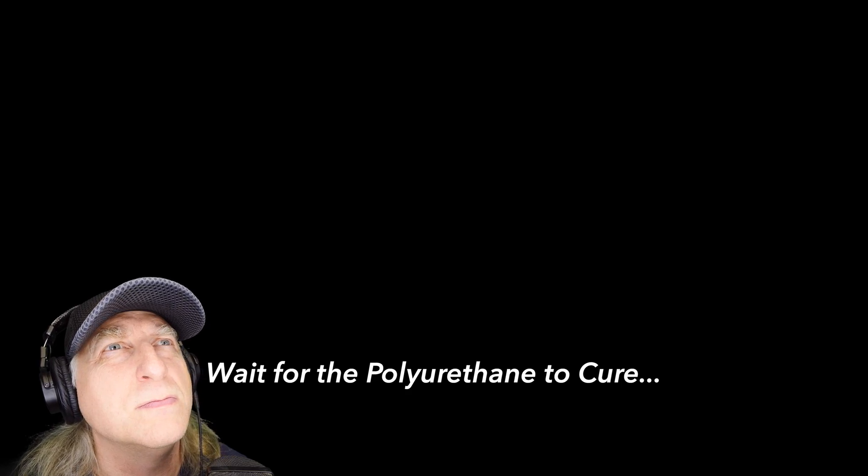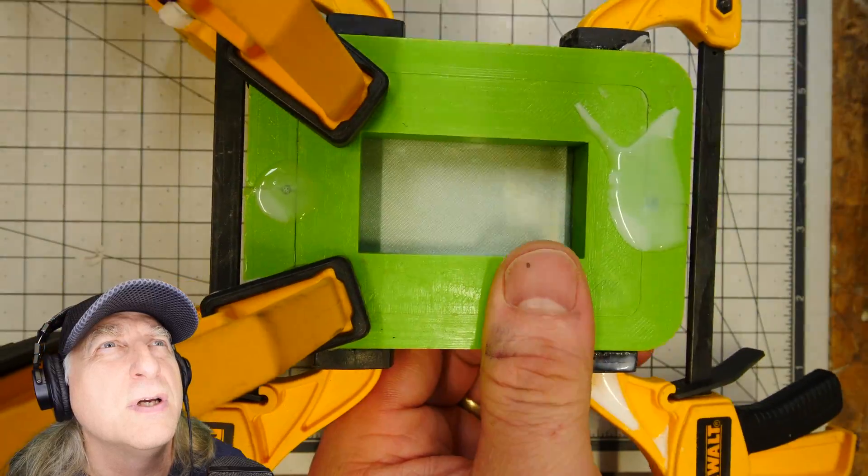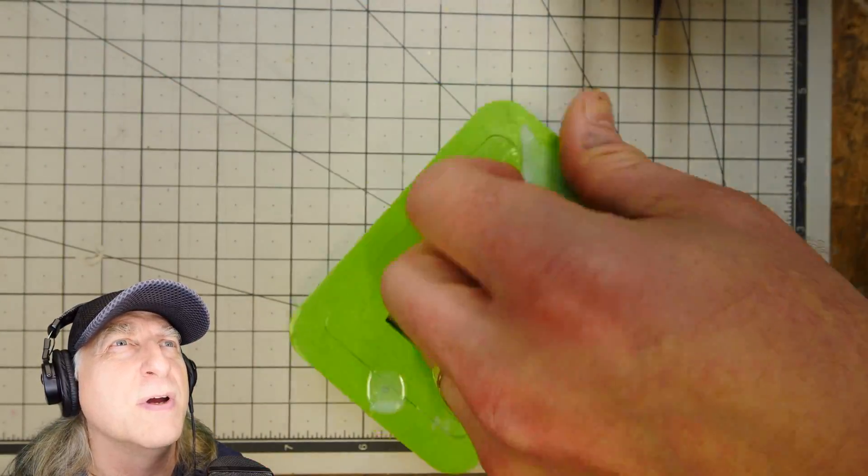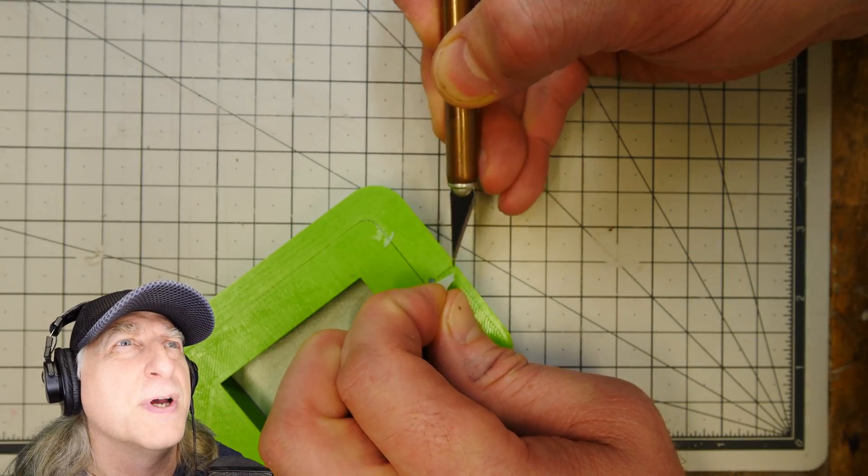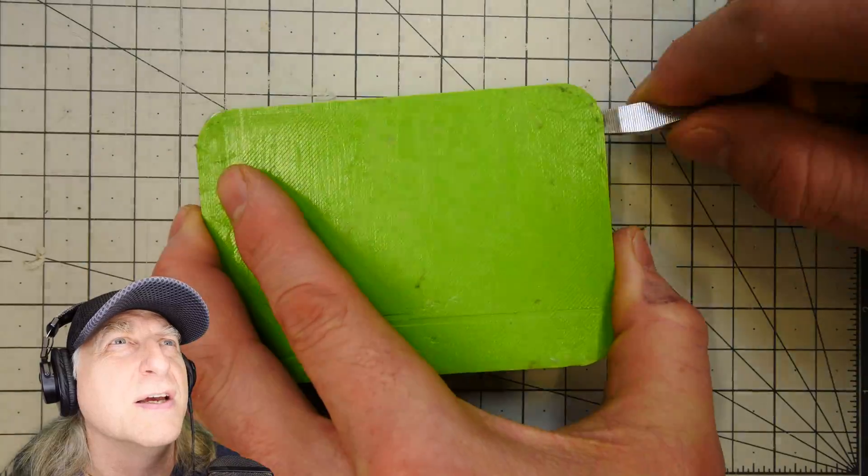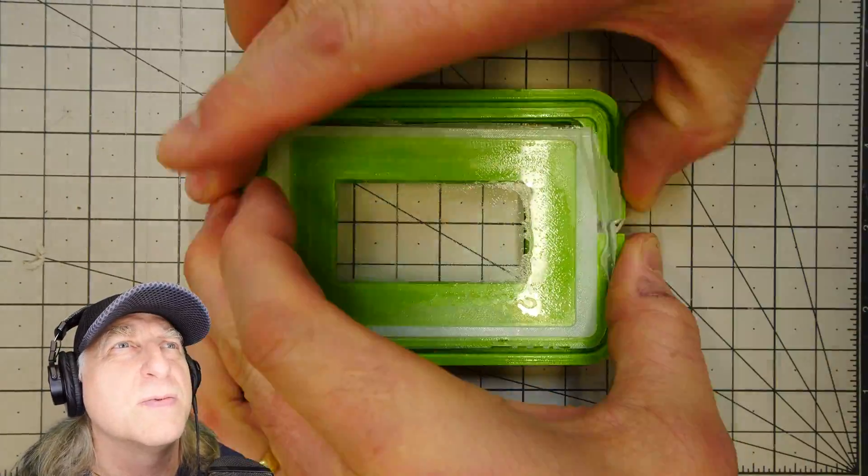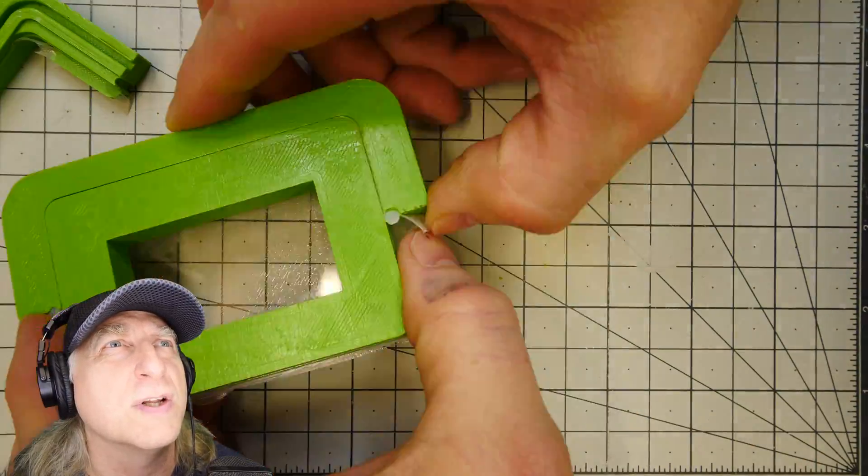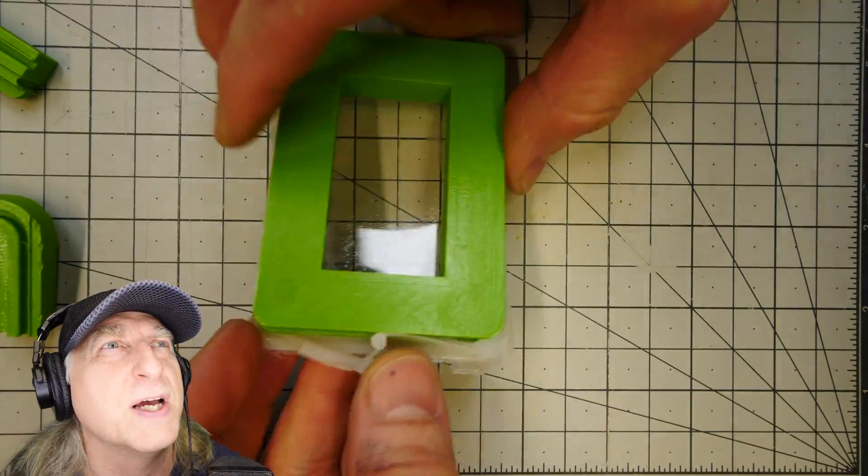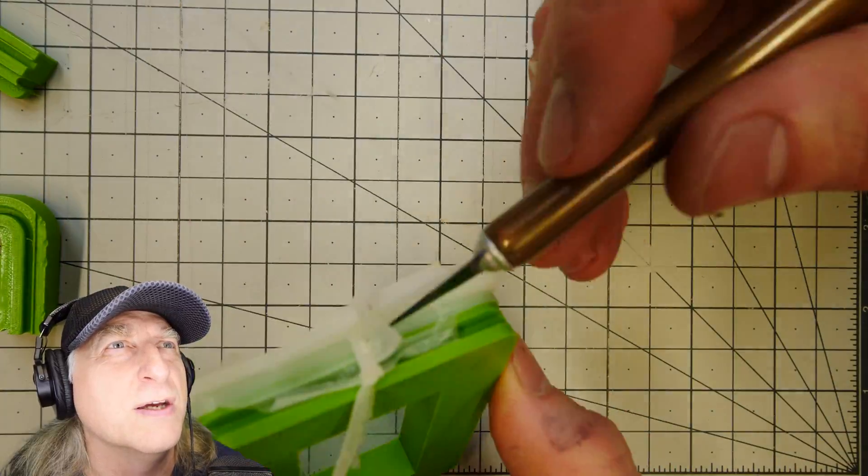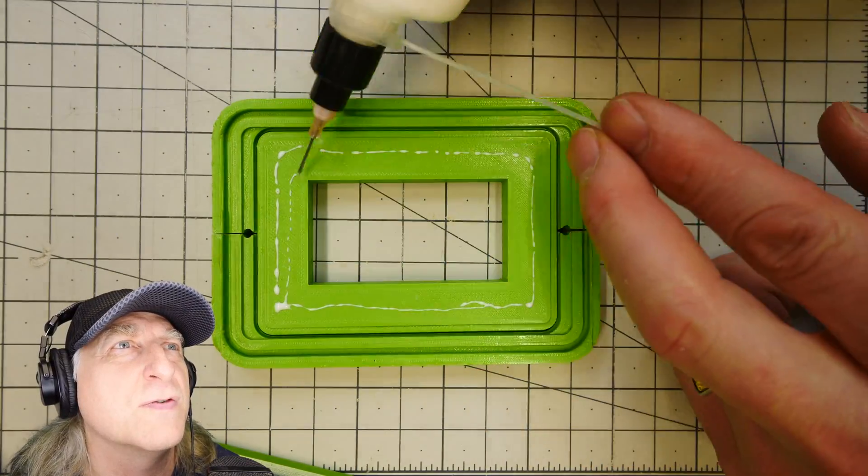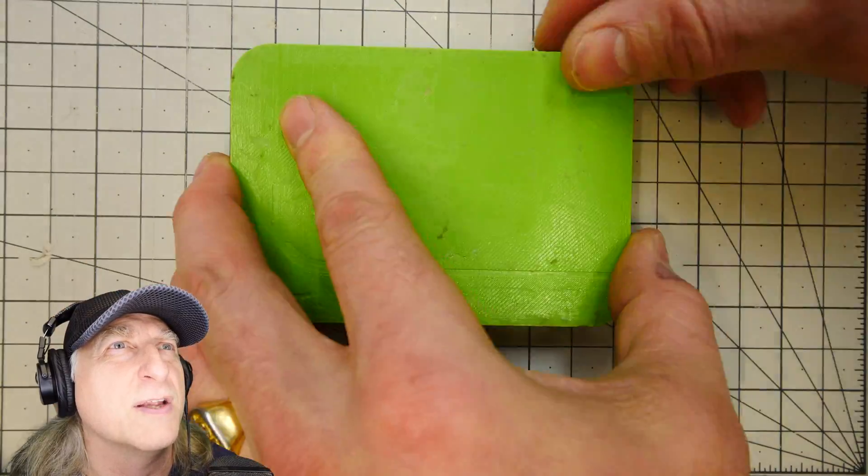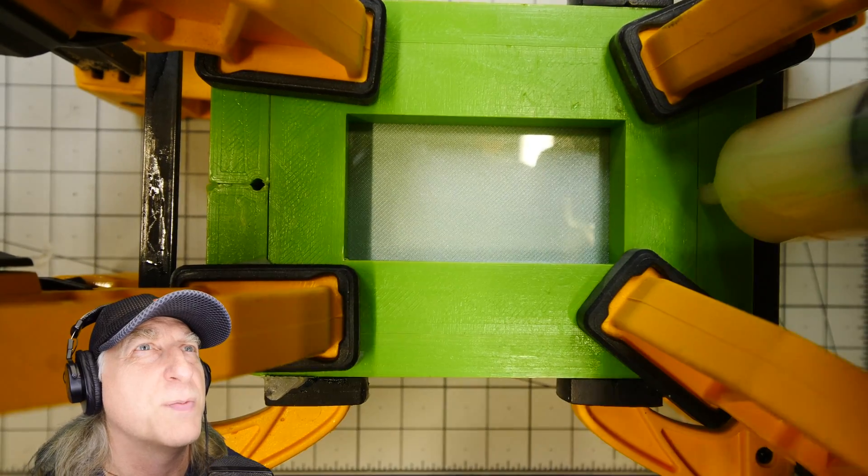Remove the clamps off the mold. Even though this mold is sort of locking, some extra clamping force is good. Remove the clamps from the top and then we'll take this apart. I can see that PVA has really helped, also just preventing the urethane from going everywhere. We'll gently pry off the side pieces here. This part has a massive undercut. There's a one millimeter ring you can see that locks that piece in, but it's a flexible urethane part so it comes right off the mold. It's molded really nice. I'm going to make another one. I need to make a minimum of two for this project.